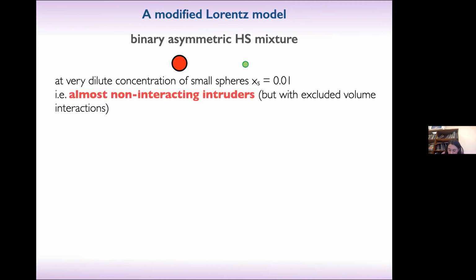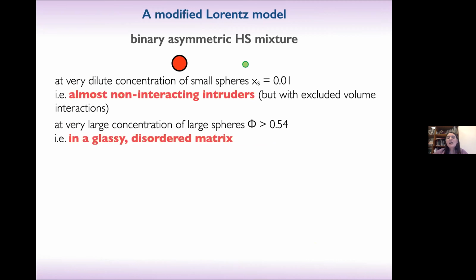Some years ago, through a collaboration with Marco Laurati, Stefan Egelhaaf, and co-workers at Düsseldorf, we became interested in a modified Lorentz model that can be realized in experiments. That is, again, another modification of a binary hard-sphere mixture, but with the following conditions. We take small spheres that are very, very dilute, with a packing fraction of 1%, so that they are almost non-interacting with each other, although they have excluded volume interactions within the matrix. And then we take the large spheres at a very large packing fraction, above 54, so that the large hard spheres are glassy and form a kind of disordered matrix, resembling the matrix of the Lorentz model.